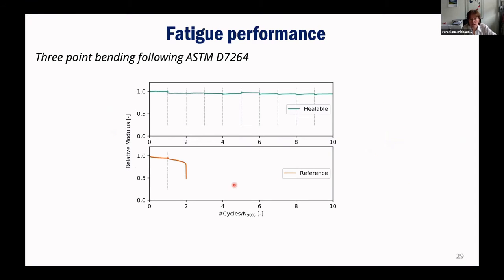And what we found is that the reference system is below. We see that we go to this number of cycles for 90% survival rate. And then we say, okay, let's put it at 150 degrees in the oven for 30 minutes. And then we bring it back, and then we do it again. And then after the second round, it actually failed. Whereas with the healable system, we put it in, we stop it, we heal it, we put it back in, we run, we stop, we heal, we run, we stop, we heal.